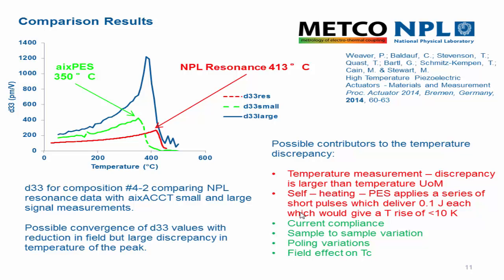And then here we're comparing it with the resonance data. We can see a trend here, and this is something that we would like to develop and measure in more detail, to see whether we have a consistent trend relating high field measurements continuously down with resonance type of measurements at a low field limit. But the data at the moment is still a little coarse.